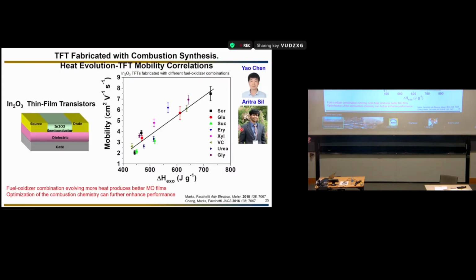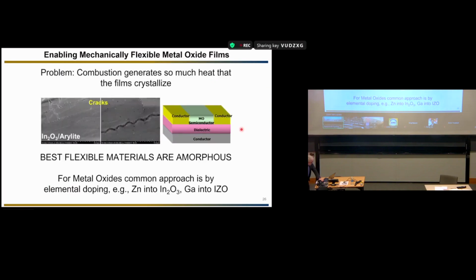And what was quite interesting, based on this oxide film, we made transistors. These are thin film transistors. So here the carrier accumulation is only in this area, but it doesn't matter. What this graph is telling you is that the performance of the transistor correlates with the heat that this redox pair is producing. So basically you can select for the same composition a different redox pair, and you can get different performance based on the heat generated. So it's a chemical way to control the formation of the product. One of the drawbacks of this technique is that we generate so much heat that usually we can also crystallize IGZO. So if you make the film thick enough, IGZO crystallizes.